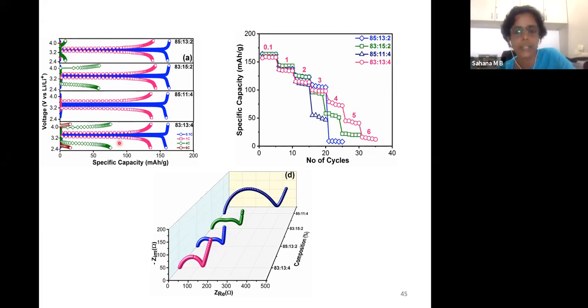So because of that, let's see how much specific capacity we get for a given C rate. The graph here on the right hand side gives specific capacity versus cycle number. Here what we do is, for the first 5 cycles, we charge and discharge at 0.1C, that is this number here. All of them have a similar capacity. Now when we charge at 1C, the loss in capacity is high, and then you can see up to 6C or 5C here. At 5C, the 83-13-4 gets some capacity, whereas not the other two. So basically, with the increase in the current or the charging and discharging rate, the capacity goes down.